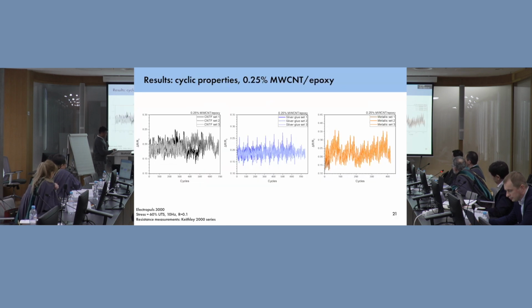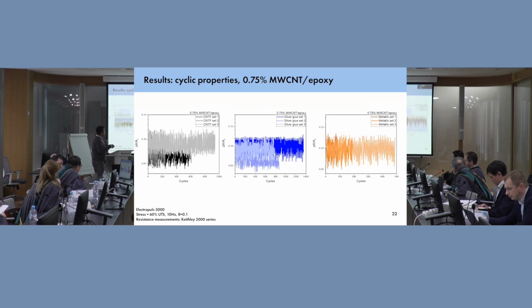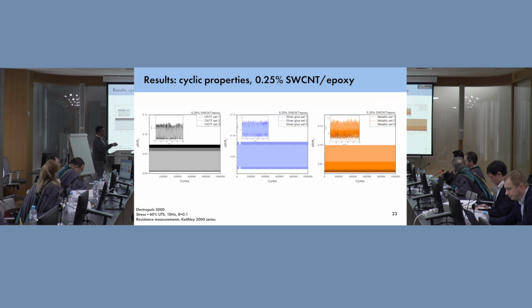So for our least conductive composites, we generally see a little variation start to take place. It's not exactly a complete baseline. For our metallics, we see this a lot more. And I assume here it should be because of some fatigue-based deformations which are taking place along the electrodes, at least in the areas where the electrodes are monitoring this material. For our very conductive composites, we don't see this, but again, the force here for testing was very low.